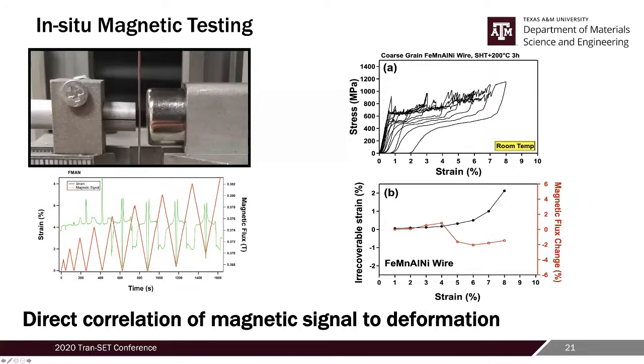Like I said, the austenite and the martensite that I talked about earlier have different magnetization levels. So for example, you load your material and you transform to martensite, and when you unload, you go back to austenite. However, if you load, in this case, 5 or 6% strain, you get some irrecoverable strain. This irrecoverable strain means that there is remnant martensite in your material. Because this martensite has a different magnetization level, you can see that the magnetic flux changes after 4 or 5% in iron manganese aluminum nickel wire.